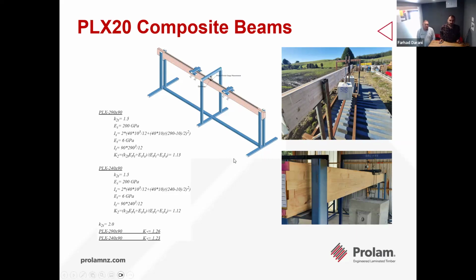And then we kind of backed up that experimental observation with these analytical procedures. We used a K2 long-term deflection factor of 2 actually in our assessments. And for the composite section, we came out to 1.26 and 1.23 for our 2 different PLX beams, which means that it performs better even when we look into it from the analytical perspective compared to 1.5, which is currently proposed in the standard. But actually, we have used K2 of 2 in our analytical procedure, so which gives also conservative results. But if your design is governed by long-term deflections, I think this solution actually kind of solves a problem very well.